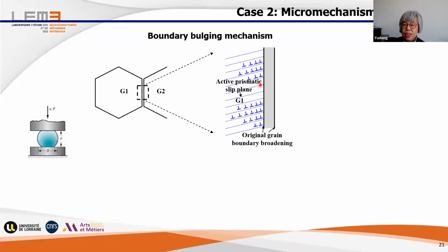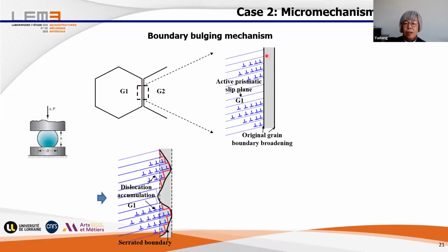And then when the prismatic slip is activated, they will create a lot of dislocations, and these dislocations will move towards the boundary area. And with such a weak boundary, these boundaries also work as dislocation sinks. Once one dislocation moves into the boundary region, we have a one-step extrusion of the boundary. If a large amount of dislocations go into this area, we finally have this bulging. And so this allows us to see clearly how stress-induced boundary migration happened.